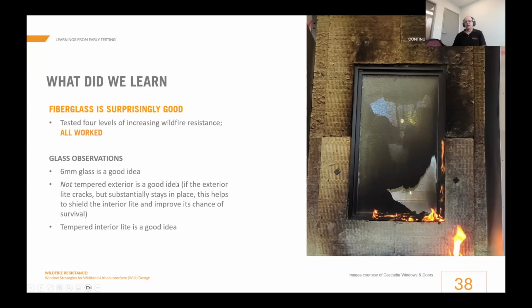And when I say it might even be a good idea, I was previously recommending this pretty hard, as in, this will actually help more. I watched some test results presented from Underwriters Laboratory that suggest that the outer light could be tempered, and statistically it's not going to be much worse than if it's annealed. But here's my thinking when I first wrote this. On the right-hand side of this slide, you see a picture where 2 layers of tempered glass in this double glazed IGU have been subjected to a test, and the test has passed. But the outer pane of glass cracked as we expected it would crack, and it cracked about halfway through the test. So it's quarter-inch thick tempered glass, both of them are.